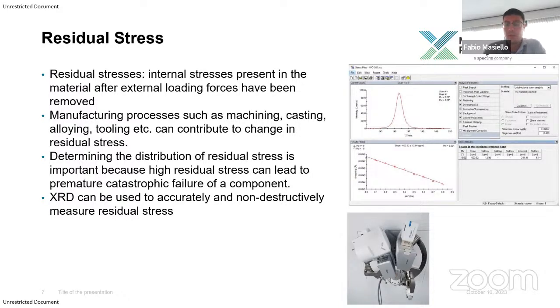Particularly, you look at the position of a certain peak, typically a high-angle peak, because it is very sensitive to this spacing, and to, for example, the inclination of your sample.